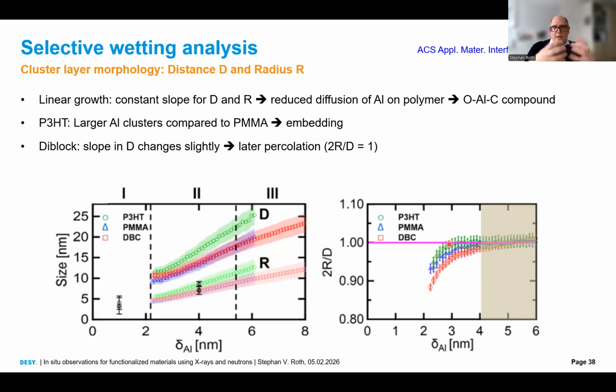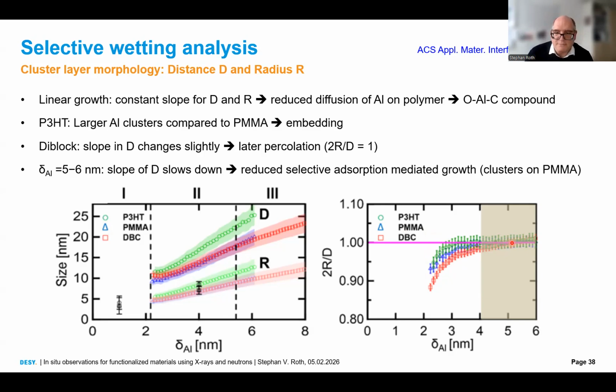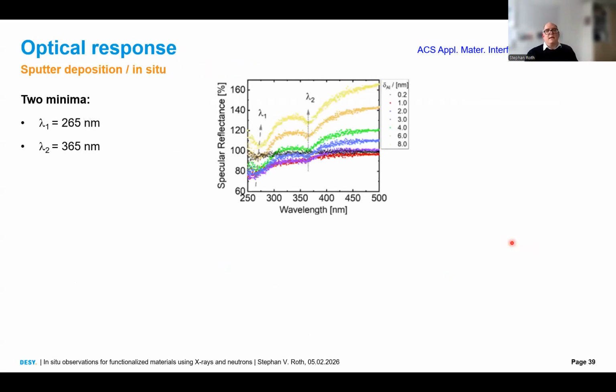Yeah, if you grow on a reduced dimension structure like these worm-like structures, the clusters grow into each other very fast. PMMA is just a flat film, and it grows later, and the diblock copolymer has some hindered structures due to its nanostructure, and therefore the percolation becomes later. Okay, so we can define this in every detail. Then we can look into the optical response.